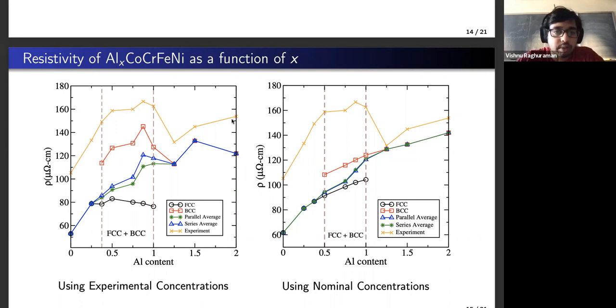And there are some other points here in that we expect the first principles calculation to be smaller than the experiment for two reasons. One, we are taking simple crystals which don't have any defects, but the actual microstructures present in the sample will have some defects, which will increase the amount of scattering. And also this curve is at room temperature, and ours is at 0 Kelvin. So we should expect some gap due to that.